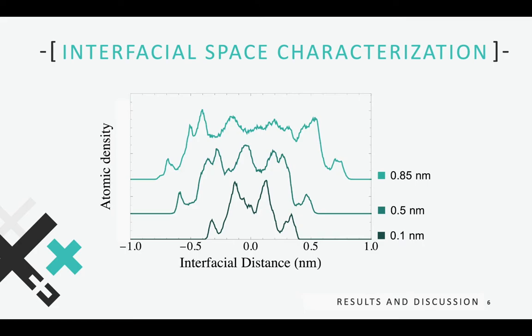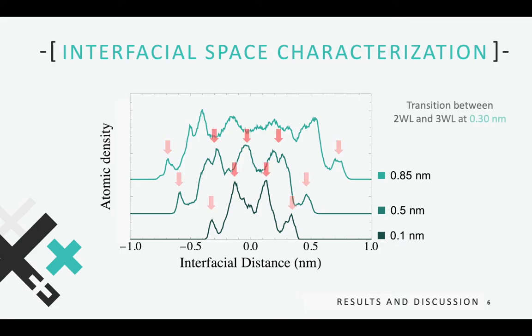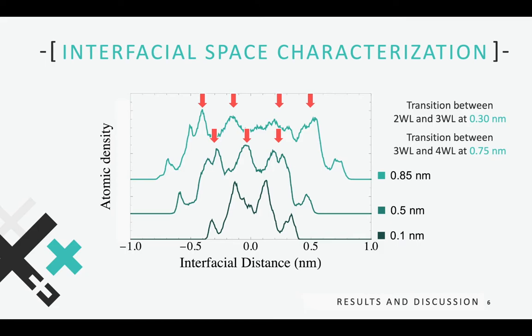We first analyze the effect of nano-confinement on the structure of water by computing the density profiles of water molecules in the perpendicular direction to the silicate layers. In all systems, there are two small peaks of local water density immediately on the surface, corresponding to water molecules strongly attached to the CSH due to the presence of surface defects. Moving toward the center of the interfacial space, there are a variable number of larger density peaks — from two to four depending on the interfacial distance. At an interfacial distance of about 0.3 nanometers, there is a transition between two and three water layers, whereas the transition between three and four layers occurs at about 0.75 nanometers.